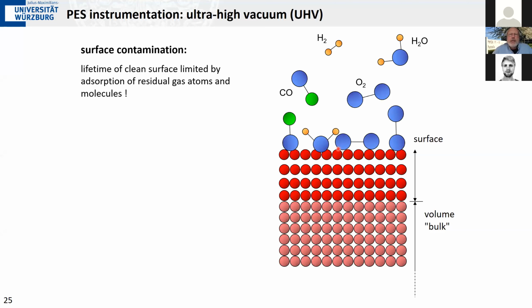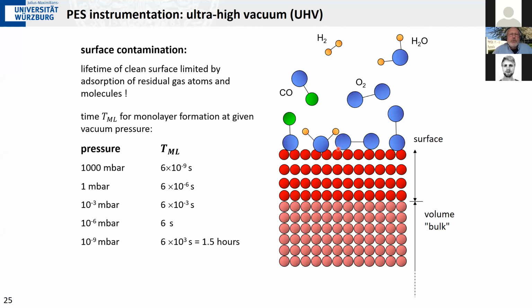And then you can look at the time scales, and if you do a simple kinematic estimate, you find that at ambient conditions, 1 atmosphere, the typical lifetime before you have one monolayer sitting on your surface is just on the order of nanoseconds. If you go to lower pressures, you increase the lifetime, but even at 10⁻³ millibars, which is already quite a good vacuum, the lifetime is still on the order of milliseconds. So that's not a time scale on which you can do an experiment.